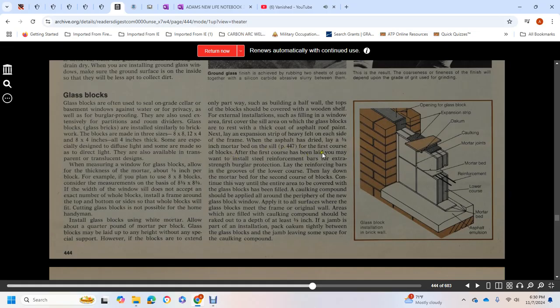After the first course has been laid, you may want to install steel reinforcement bars for extra strength and burglar protection, laying reinforcement bars in the groove. Lay down the mortar bed for the second course of blocks and continue this way until the entire area to be covered with glass blocks has been filled. A caulking compound should be applied to all areas around the periphery of the glass block window, wherever the glass block meets the frame and the original wall. Areas to be filled with caulking compound should be